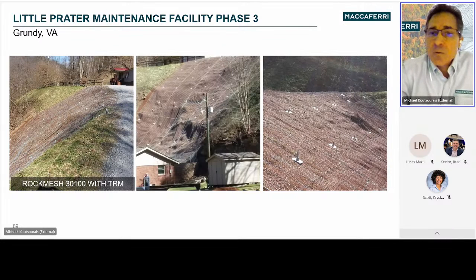The shallow landslides resulted in larger portions of the hillside dislodging and traveling downslope, leaving an oversteepened scarp behind them. Then new shallow landslides initiate upslope from previous ones as the new slope geometry is often unstable. The slope at the project site ranged from 28 up to 83 degrees where the scarps were present. Generally, the slope was at an angle near 38 degrees and about 100 foot long by 60 foot wide. The solution consisted of soil nailing with the placement of RockMesh 30100 and MacMat for surface stabilization and revegetation.